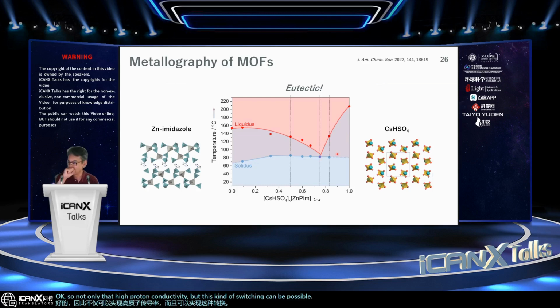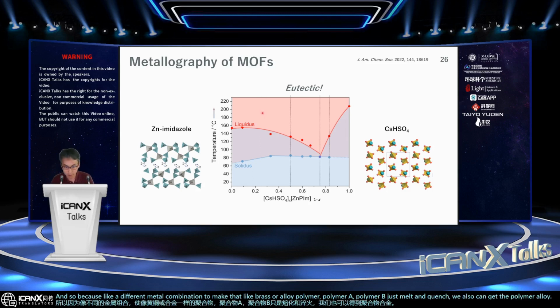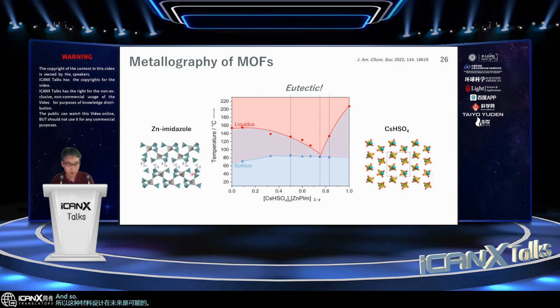So actually, if this type of metal molecular crystals shows the melting, glass and crystal reversibly, we can investigate or develop this type of MOFs as a material from the viewpoint of metallurgy, okay? Because like a different metal combination makes brass or alloy, polymer A, polymer B, just melt and quench, we also can get the polymer alloy. So this kind of material design can be possible in the MOFs. And one example for the proton conductivity, as the last topic, is shown here.